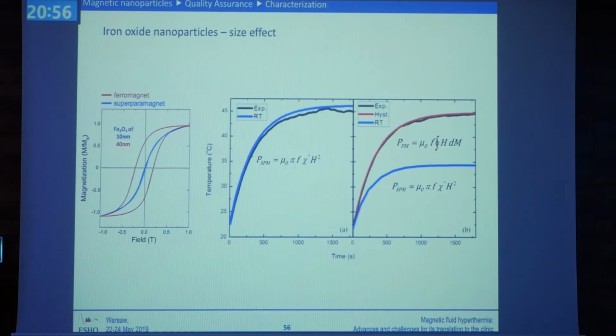Another issue that needs to be taken into account is when you do your simulations, these are numerical simulations with COMSOL, you have to be sure what sort of physics there is behind your heating. For example, if you have 10 nanometer iron oxide nanoparticles, this is the blue line, you can see that there is no hysteresis here. If we use the literature values for the power that is deposited inside your medium for superparamagnetic nanoparticles, okay, you can see that you have a very nice agreement between your experimental value, which is measured with the optical fiber, and your numerical results.